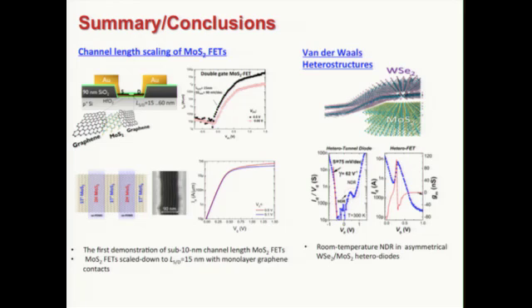Two questions. One: in 2D material, I guess you won't dope your material like we did in semiconductor, right? In conventional semiconductor you dope. You mean you implement doping? Right. In 2D, normally doping is by surface treatment. So you still need to dope it, but you don't need to implant ions or dopant inside the crystal. That would destroy the crystal, especially if you're working with a monolayer. But since they're very thin, you can basically put down the dopant layer right on the surface, and that would dope the system. It's all based on surface modification.